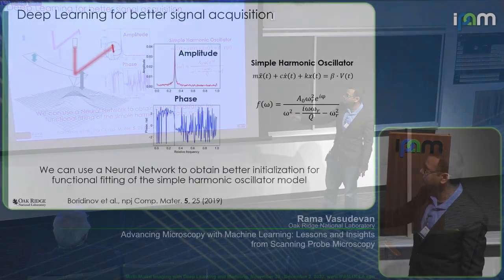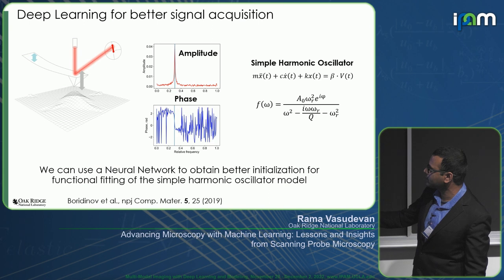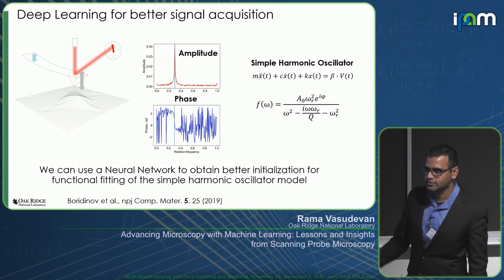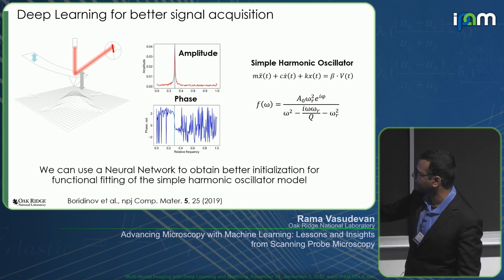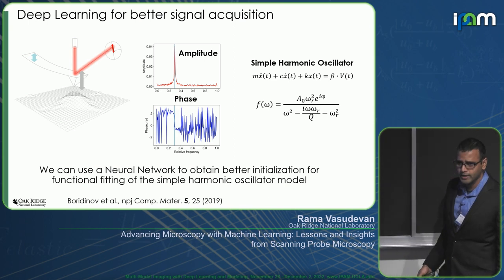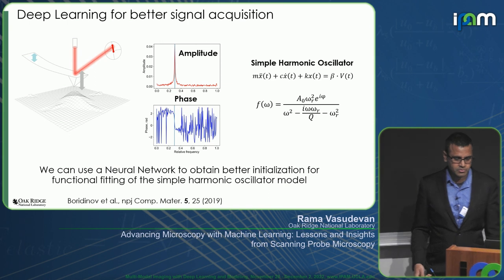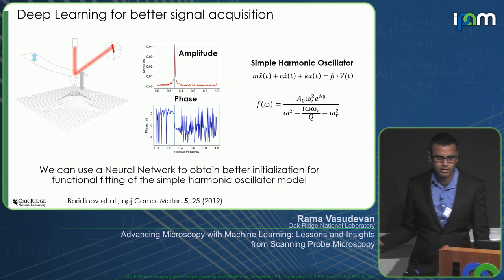And so typically what we do is we get this data, and then we fit to this particular model, and we extract parameters such as the amplitude of the oscillation, the phase of the oscillation, the resonant frequency, in other words, where this amplitude is maximum, and then something called the quality factor of the cantilever, which is related to the full width half maximum of this particular peak. So this is all well and good.